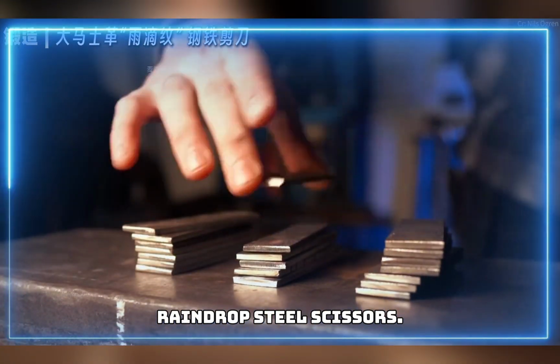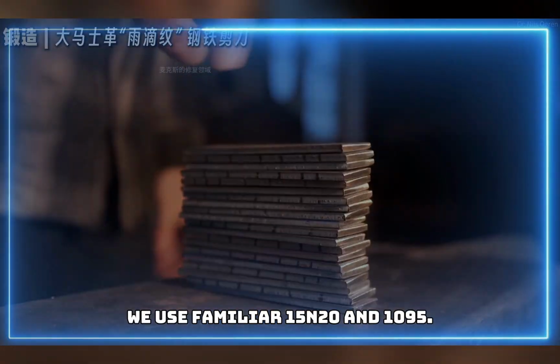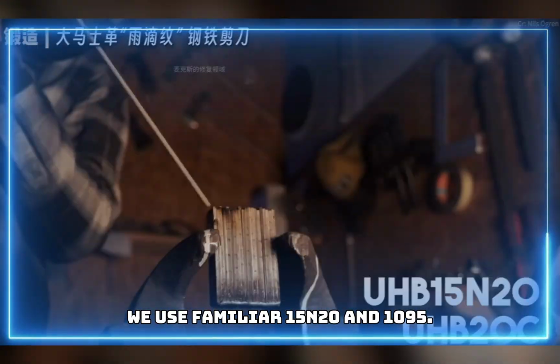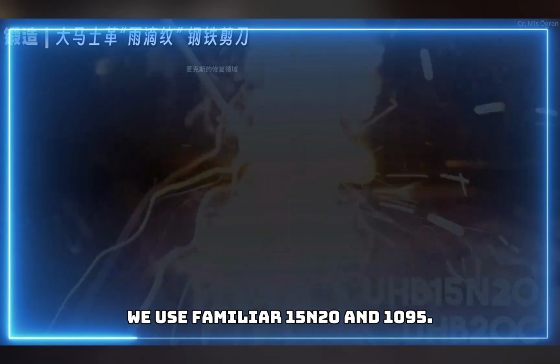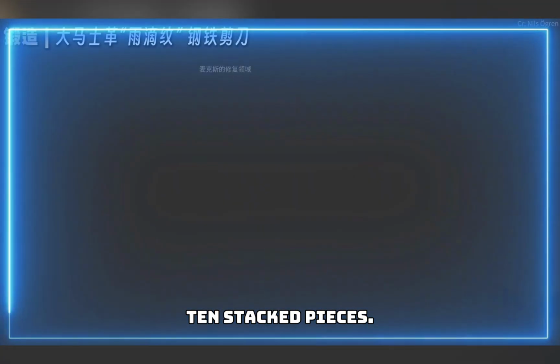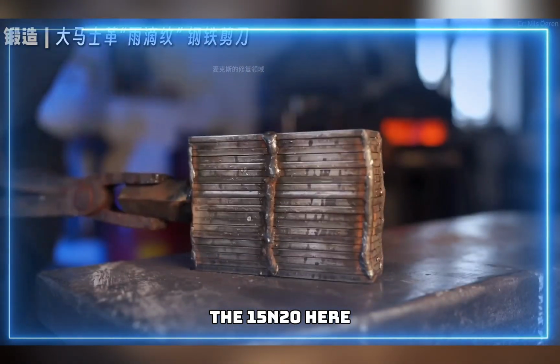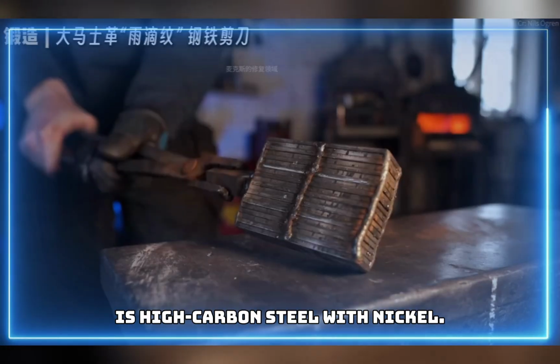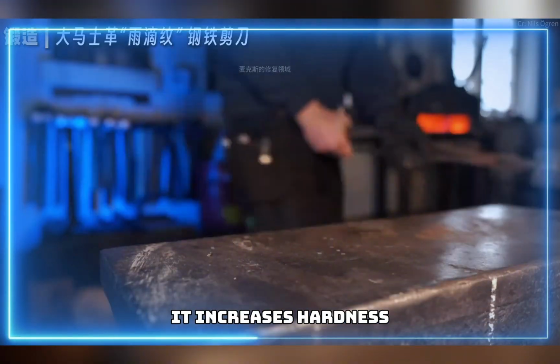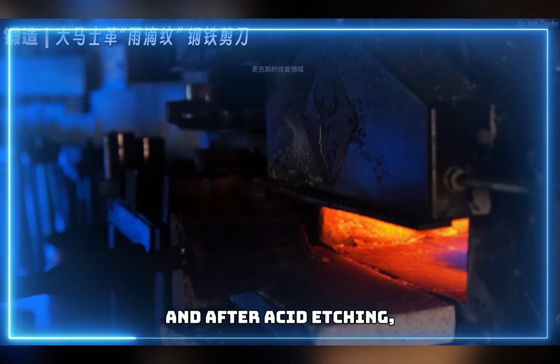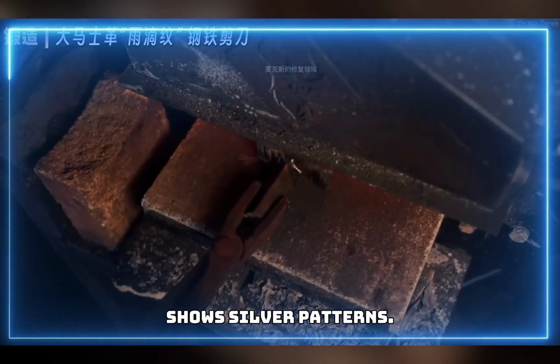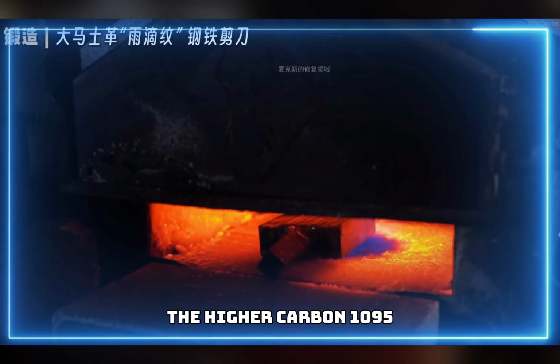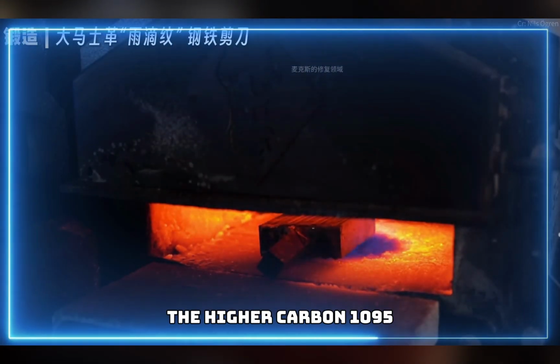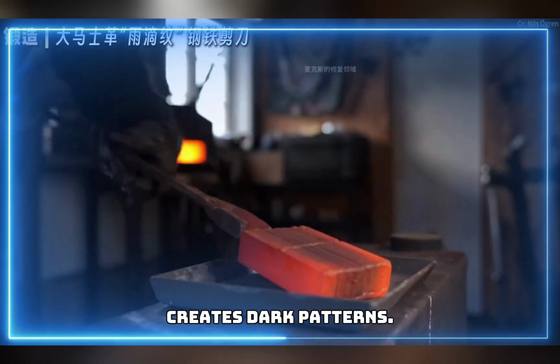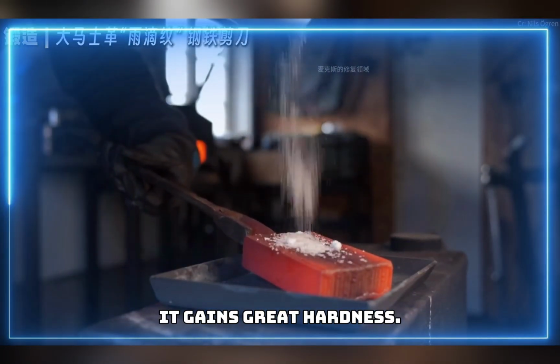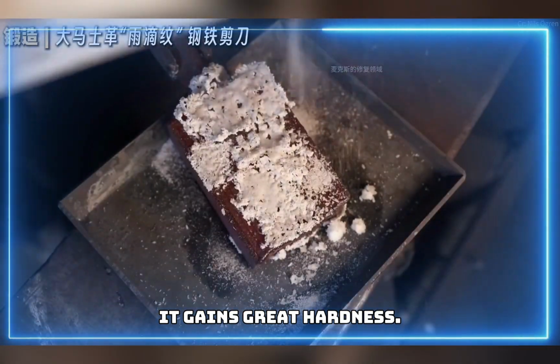Raindrop steel scissors. For materials, we use familiar 15N20 and 1095. 10 stacked pieces. The 15N20 here is high carbon steel with nickel. It increases hardness. And after acid etching shows silver patterns. The higher carbon 1095 creates dark patterns. After quenching, it gains great hardness.